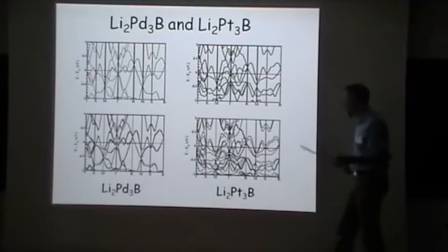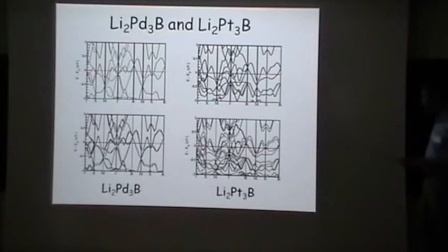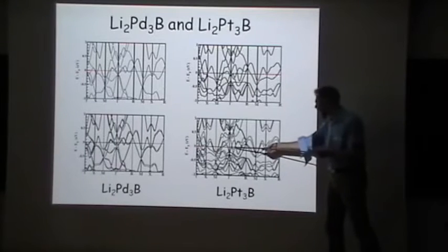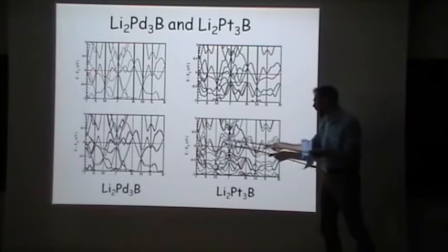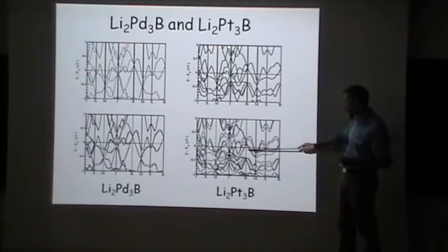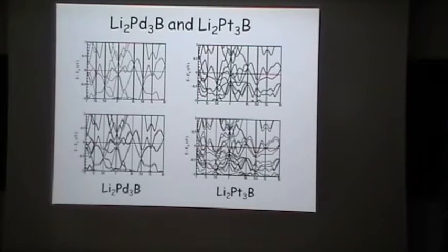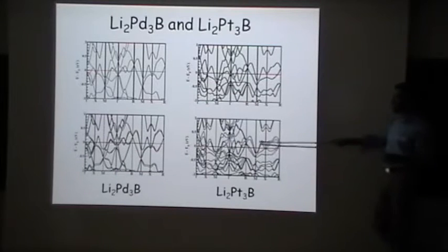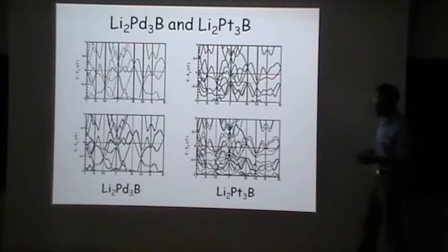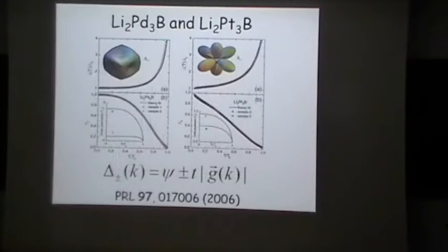Another thing I want you to notice is if you look carefully as you move along these bands, you see that the spin orbit splitting is anisotropic. It's smaller in some regions than in other regions. So G of k does depend on momentum, and it's not uniform. And so, using the fact that the spin orbit coupling is larger here than here, we suggested the possibility of what's happening